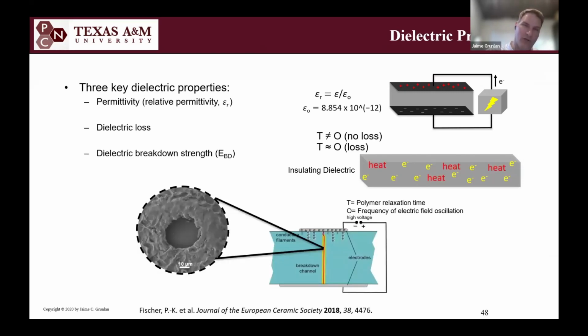So there's a property called dielectric breakdown strength, and you can see an example here as I'm applying a voltage to a film. Eventually, I'm going to burn a hole through that film, and then there's going to be a short if that's an insulating film, if that's a dielectric film. And so we have a test in our laboratory where we can ramp up voltage and then see at what voltage that hole forms, and then I'll get a kilovolt per millimeter dielectric breakdown strength.